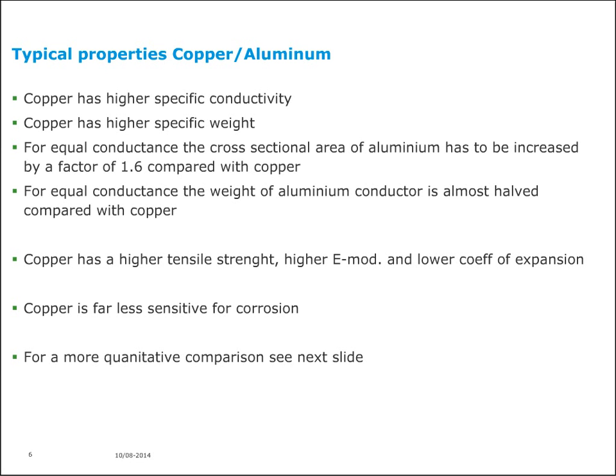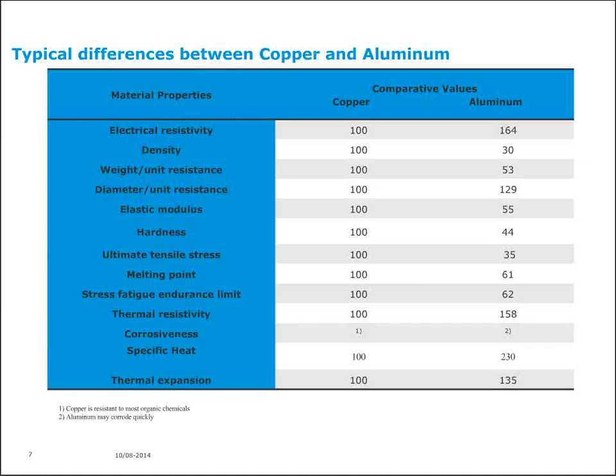Copper has a higher tensile strength, higher elasticity modulus, and a lower coefficient of expansion. Copper is far less sensitive for corrosion. This is a very important difference. Aluminum is corroding quite rapidly, and copper is not doing that. For a more quantitative comparison, I would like to show you the next slide.